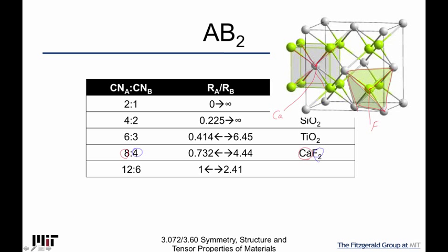And that's the fluorine. So this is the fluorine in here. It's bonded to these 4 atoms there, and you can see how it fits into the cubic crystal structure that is face-centered with the calcium, right? But we have the fluorines taking these tetrahedral holes.